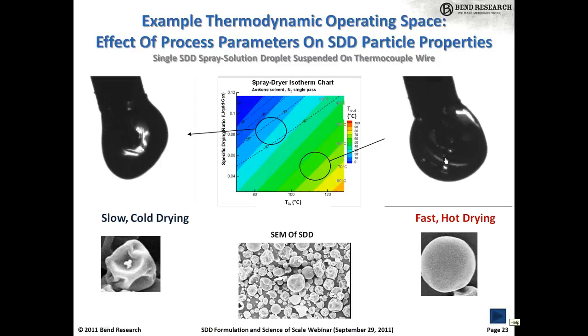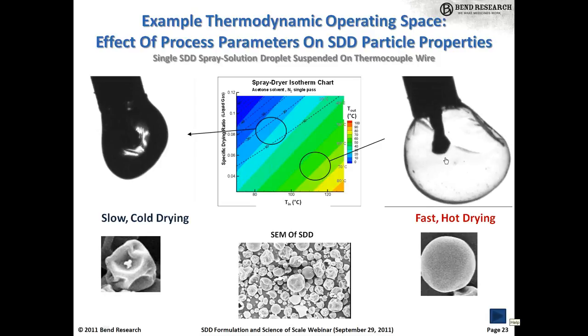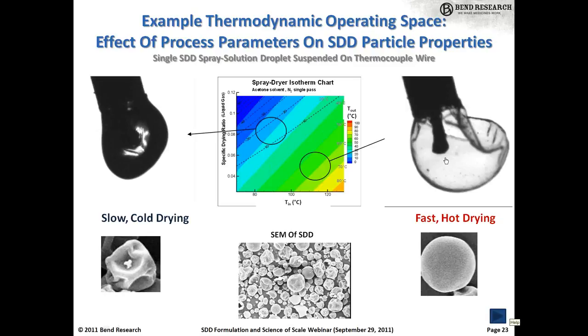So on the right here we're showing a hot outlet temperature which results in hot fast drying, where the skin sets up almost immediately as the solvent evaporates and acts as a barrier to solvent evaporation, such that the solvent actually evaporates inside the skin and the pressure inside the droplet is higher than the pressure outside, and you end up with these hollow spherical particle morphologies that are very compressible.